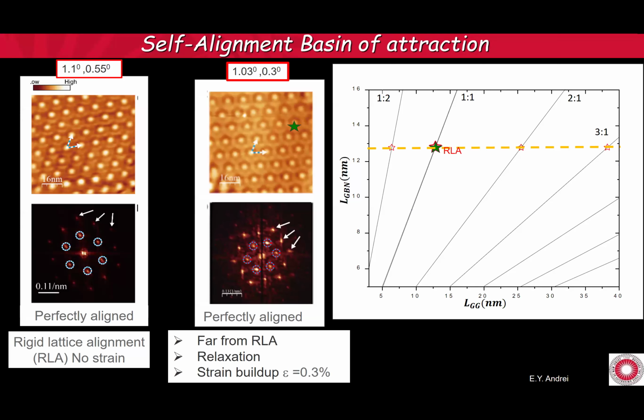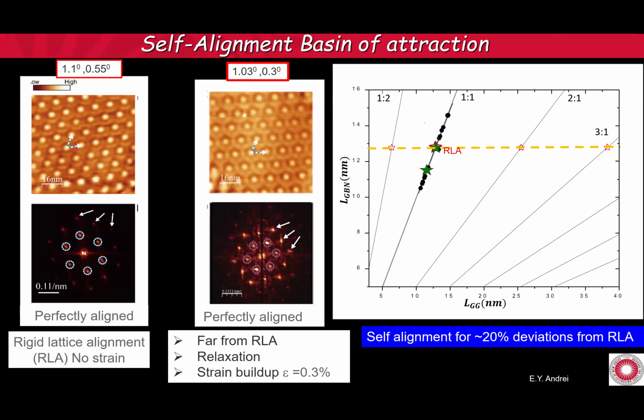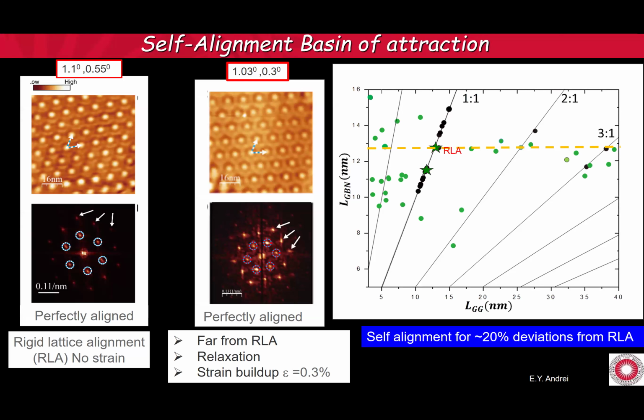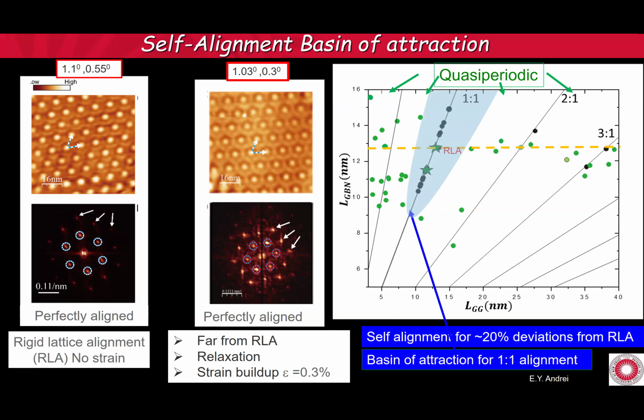Now we have another aligned one, 1.03, 0.3, that I showed before. It sits right here. And then we have about a dozen other ones that sit along this line. The only one that's unstrained is this one. And then, of course, we fill this phase diagram with samples. So let's first focus on the 1-to-1 alignment. If you look closely, you'll notice that we have no points within this, what we call basin of attraction. So every lattice that would have been here presumably is going to find its lowest energy and gravitate to 1-to-1. We don't have a basin of attraction for any other ones. So it's only for the 1-to-1.